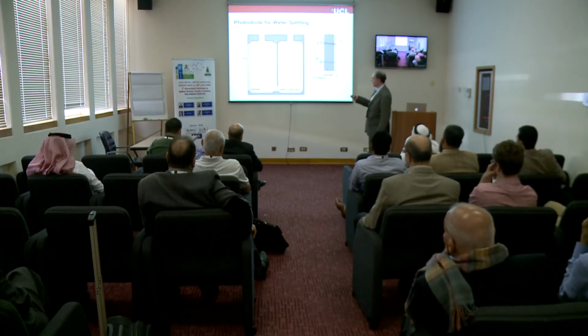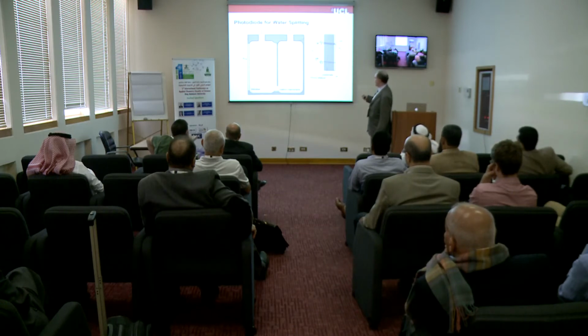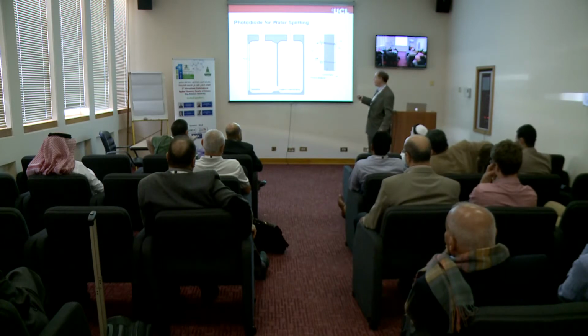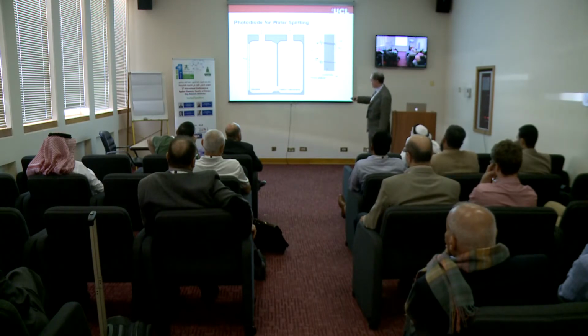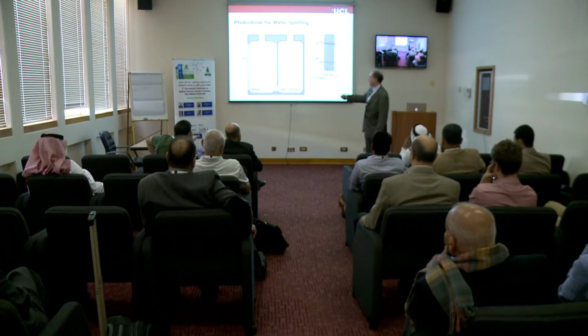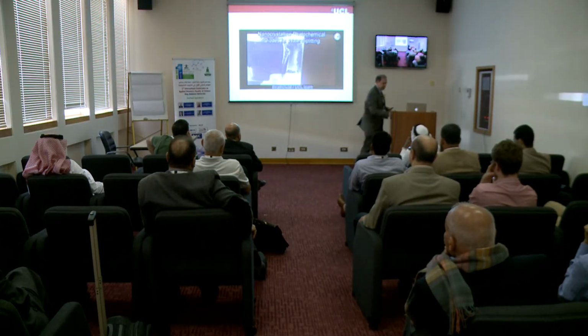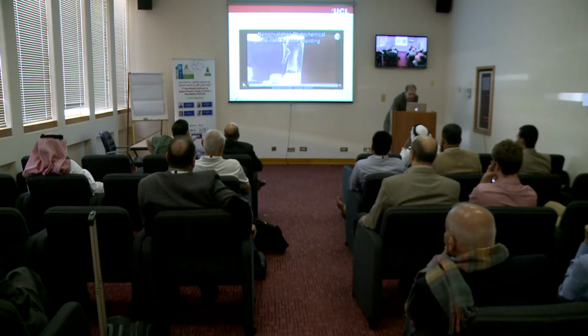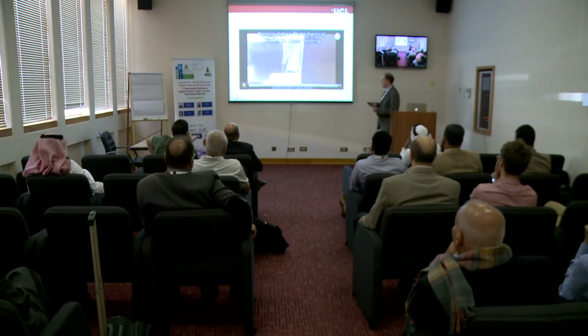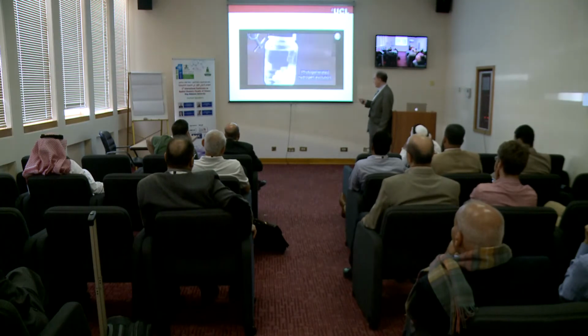So the way it works, we have sunlight coming in. The sunlight hits the surface of the titanium dioxide. At the surface of the titanium dioxide, it creates an exciton if you're a physicist, or an electron-hole pair. This electron goes over to this side through a membrane, and it causes photoreduction of water, generating hydrogen. And on this side, we get the photooxidation of water producing oxygen, and they're produced in two different compartments. So you could potentially use the hydrogen as an energy source, and use sunlight to do it, and using water as effectively as a transfer vector. So this is a video which will show that.